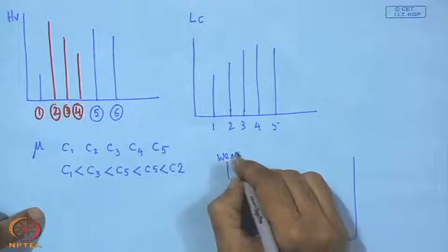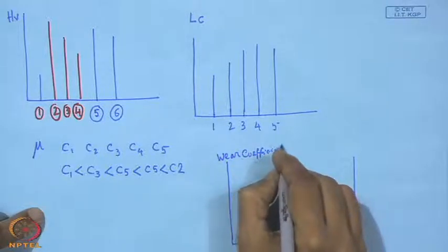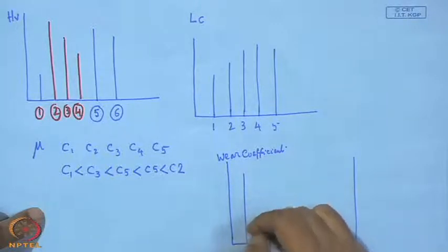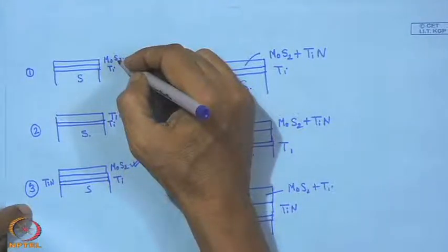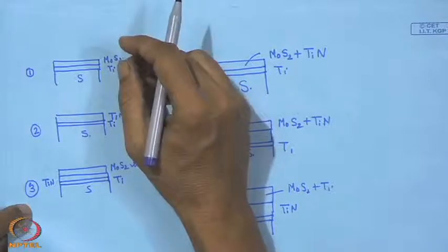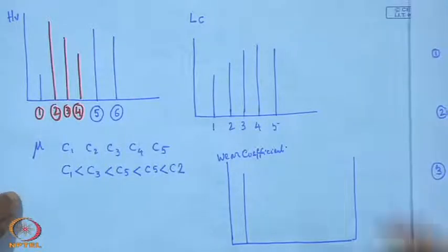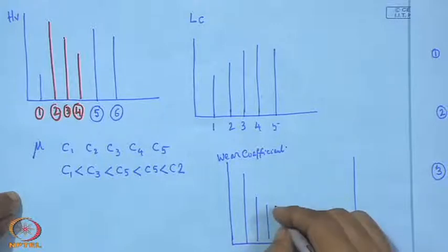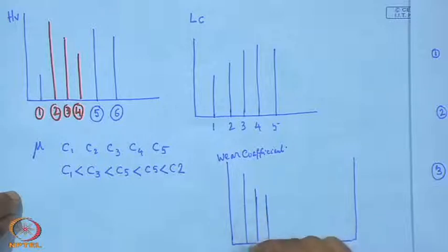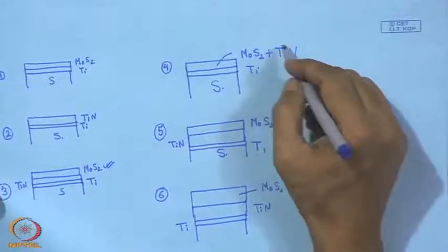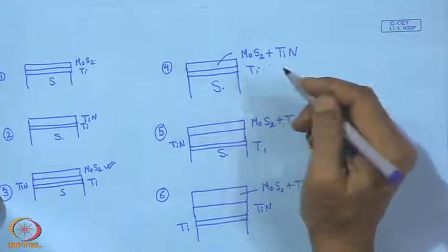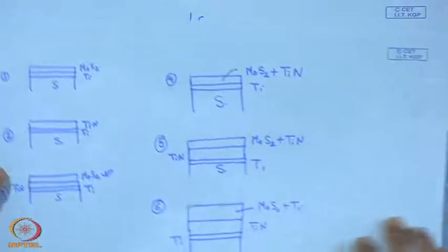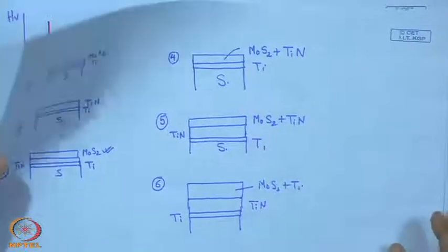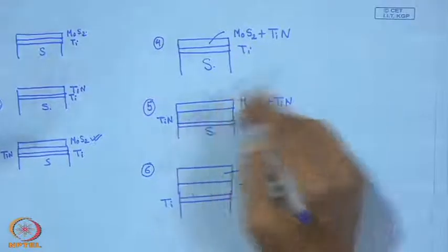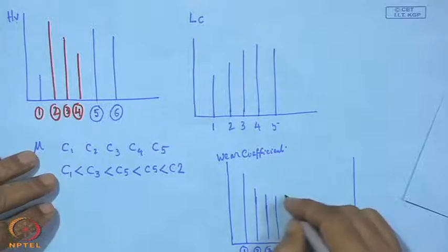This is wear coefficient. So, here what we find is that the wear coefficient of this coating number 1 is not that wear resisting, though the friction value is quite low, but that is only for a small period of time. And then we have here 2, 3, and then we have here 4. This is the number 4, that is a composite coating without any support. And finally we have here this 5, and this 5 means it is composite coating with a support of titanium nitride, and that gives also quite low value of this coating.